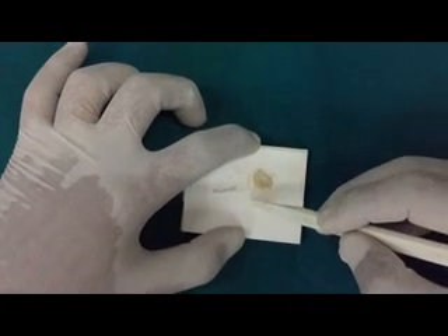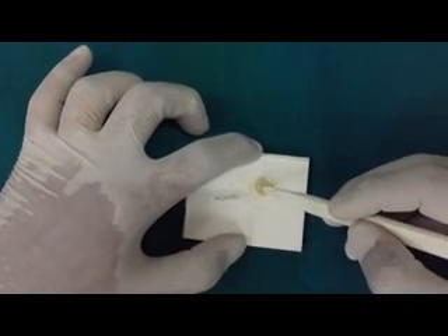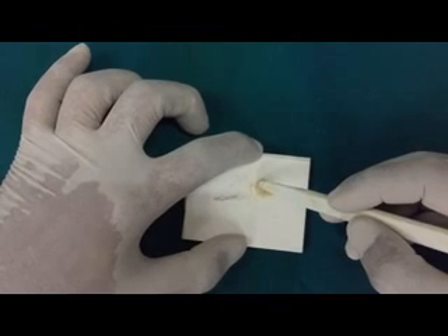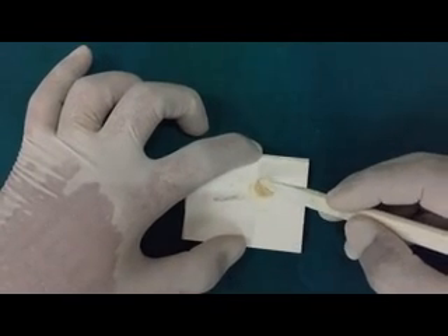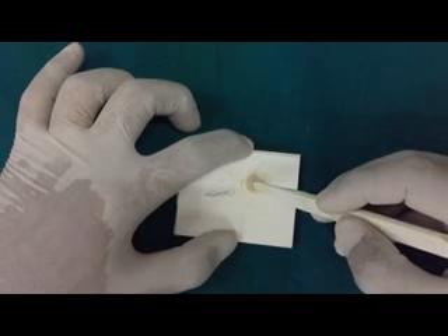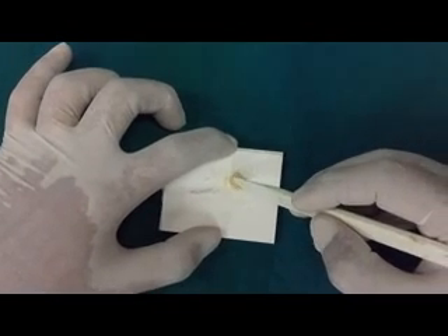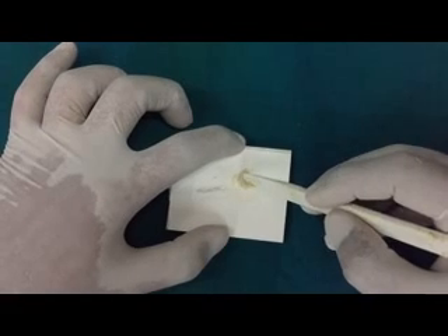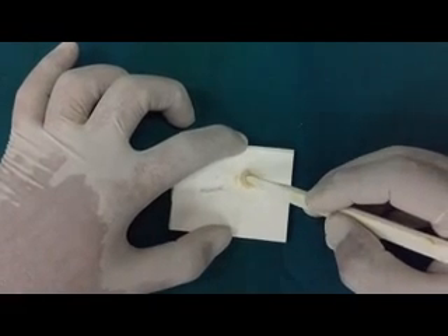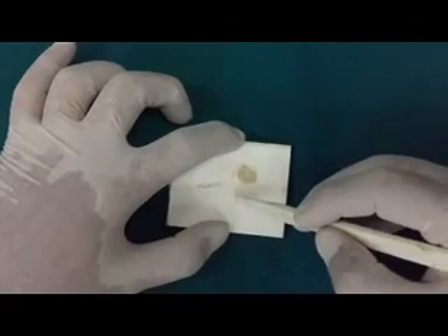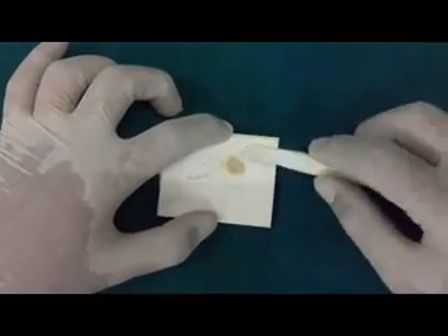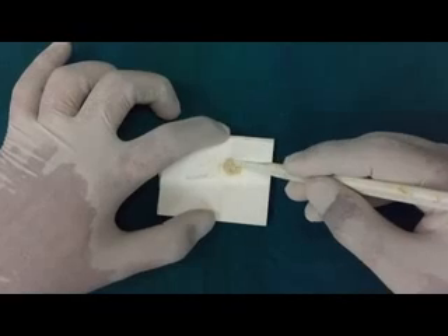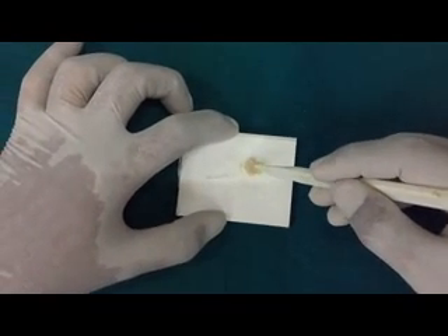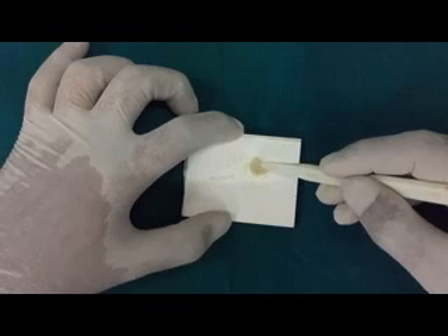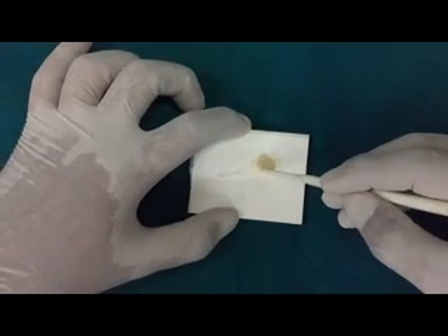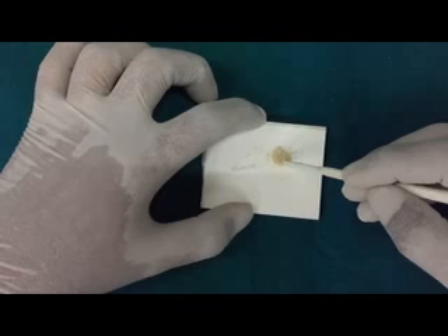If the cement is contaminated by saliva during the first 24 hours, there could be a loss of the cement particles and hence it would be physically of lower strength. At the same time, if the water that is loosely bound in the initial stage is lost by desiccation of the cement, it could create cracks or craze lines on the restorative material and hence reduce the physical properties of the cement. So for the first 24 hours, the cement has to be protected using a water impermeable membrane.